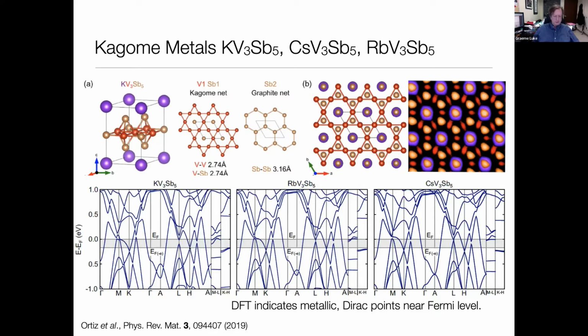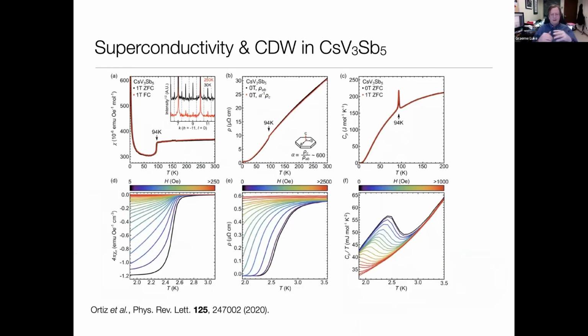You have these band crossings, these linearly dispersing bands. DFT indicates that these materials are metallic. So, for that matter, does experiment. And you see these Dirac points where these bands are crossing near the Fermi level, which also brings up the idea that there could be some interesting physics here. So these materials were discovered in 2019, and some quick characterization of them indicated that, shortly after that, there's an awful lot of interesting behavior happening in these materials.